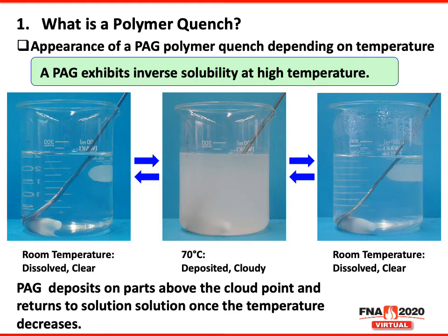Now, a polymer exhibits what's known as inverse solubility. You can see on the left that the polymer is very clear. On the right, when it's heated up to 70 degrees C, which is roughly between 150 and 160 Fahrenheit, it turns cloudy. That means the polymer has come out of solution. And then when it returns back to room temperature, the solution becomes clear again.